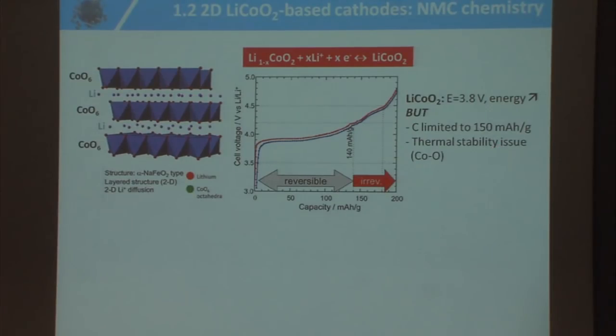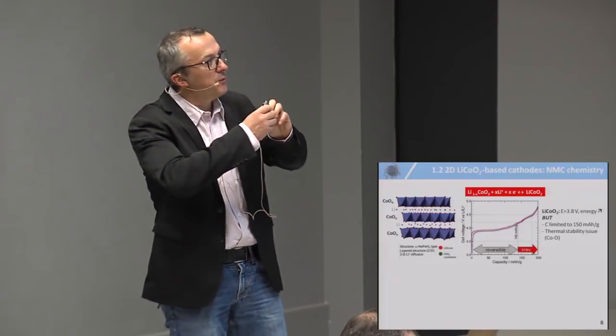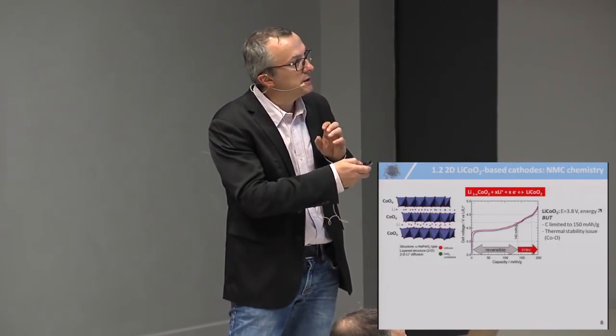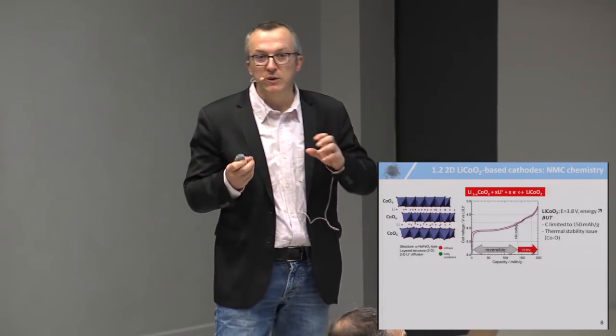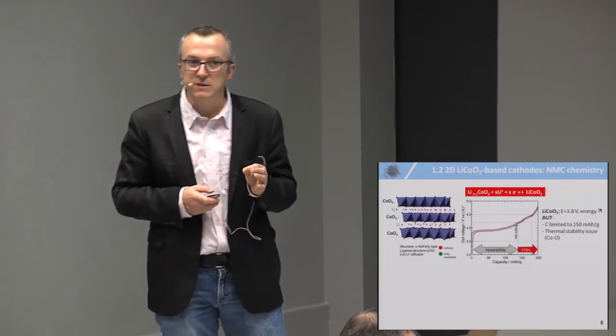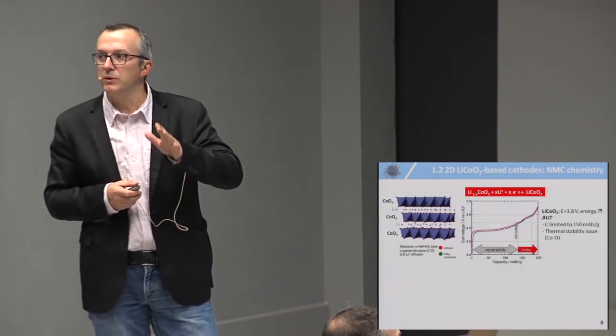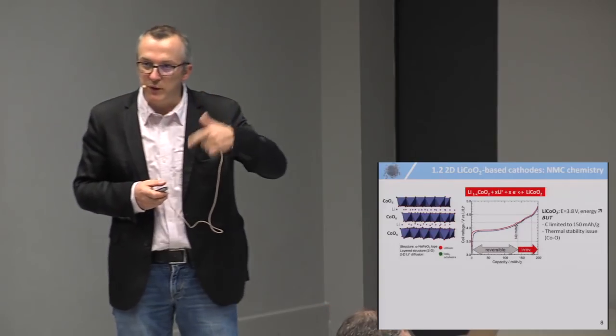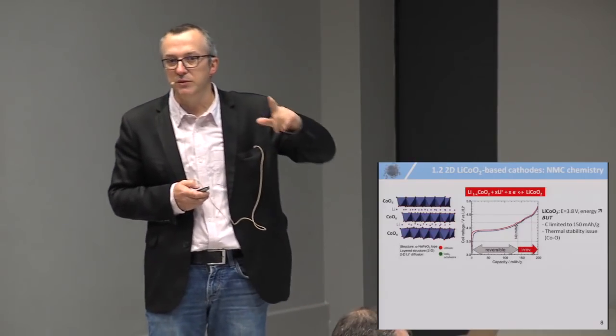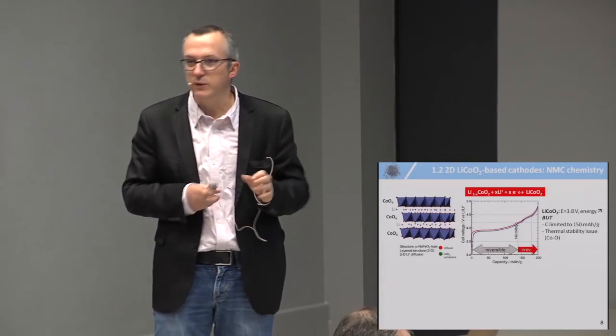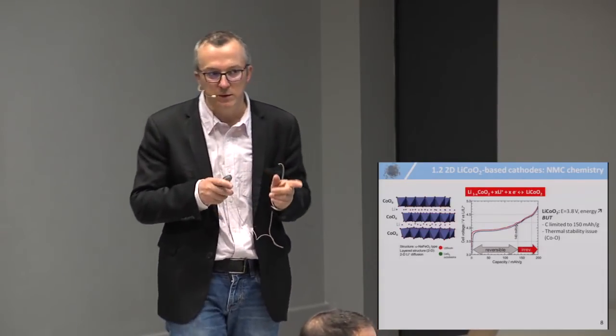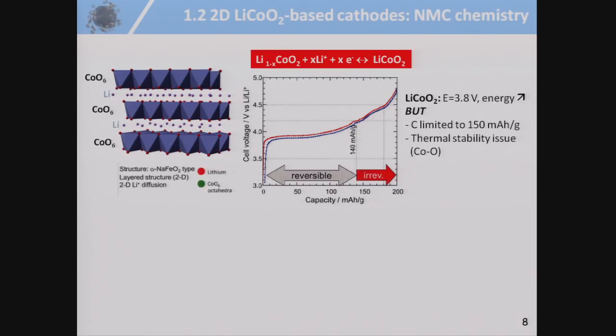But the key here is the thermal issue. When you heat LiCoO2 beyond 170 Celsius degrees, you are going to have a break of the cobalt-oxygen bond, and this breaking is going to release a lot of heat. And this is called the thermal runaway of a battery. It means as long as you go beyond 160 Celsius degrees, the battery goes into thermal runaway. It means that the cell temperature can reach 800 Celsius degrees, and you cannot extinguish the fire. This is what is called the lithium fire. It was one of the problems of the Dreamliner. In fact, it was the problem of the Dreamliner.